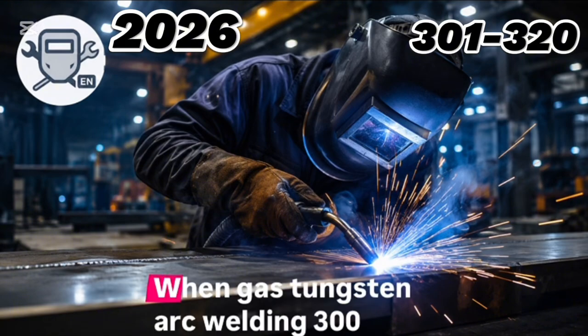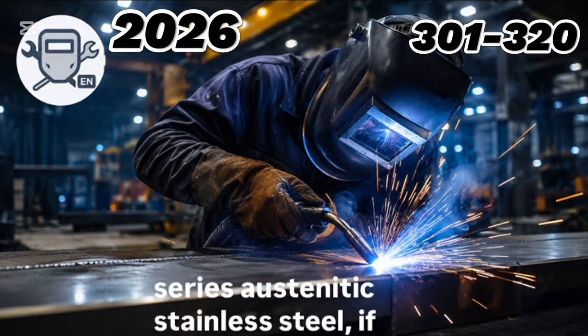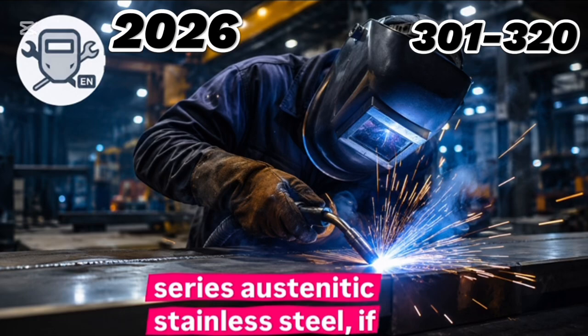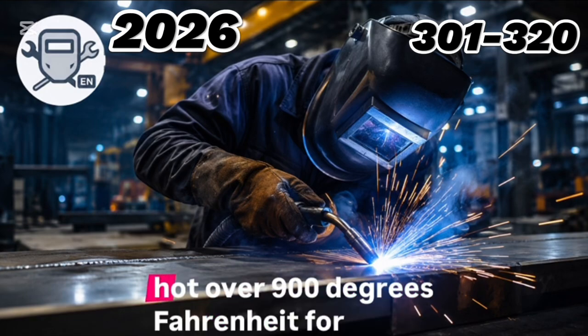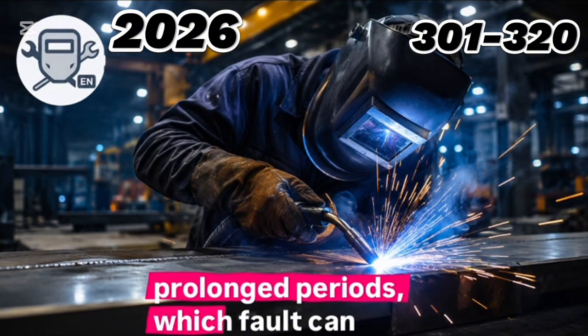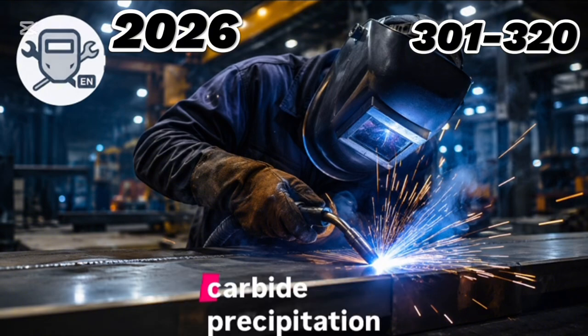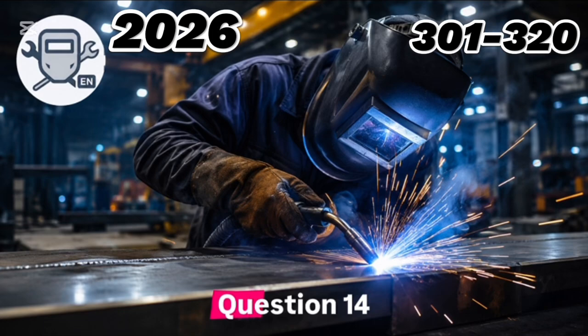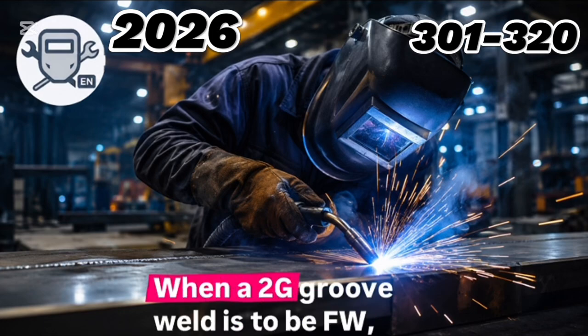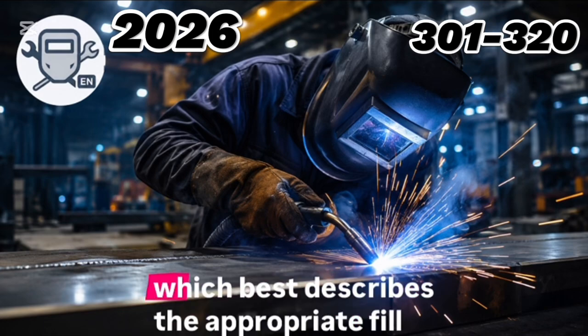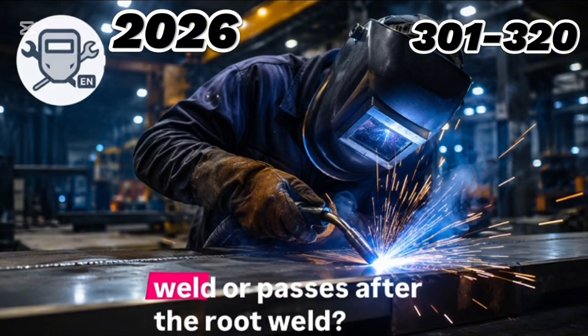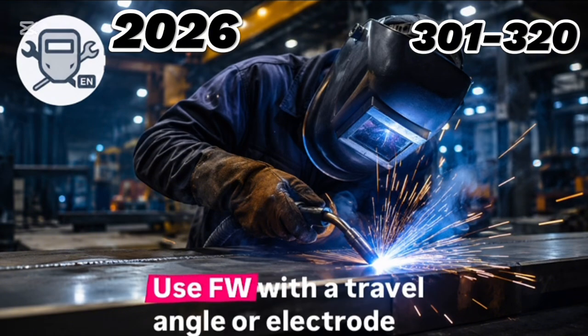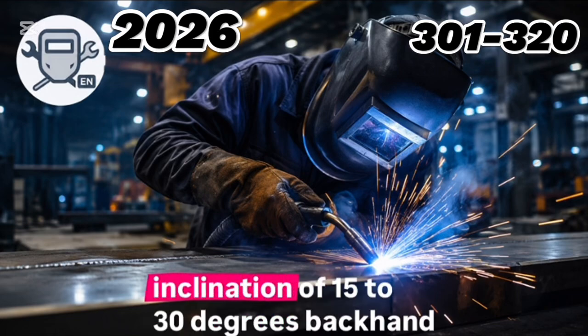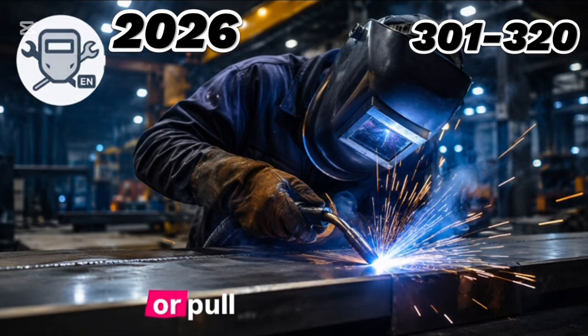Question 13. When gas tungsten arc welding 300 series austenitic stainless steel, if the weld and base metal are maintained hot, over 900 degrees Fahrenheit, for prolonged periods, which fault can occur? Answer: carbide precipitation. Question 14. When a 2G groove weld is to be FCAW, which best describes the appropriate fill weld or passes after the root weld? Answer: use FCAW with a travel angle or electrode inclination of 15 to 30 degrees backhand or pull.